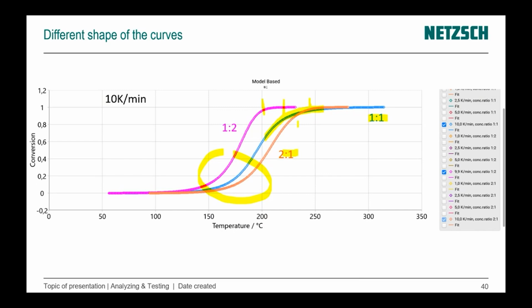Here we have the concentration ratios, which are close to the optimal values, and then we have the total order of reaction, like a sum of the first order regarding the first reactant and the second order regarding the second reactant. But if we have another concentration ratio, then we have a high excess, and then changing the concentration of the reactant with high excess has almost no influence on the order of reaction.